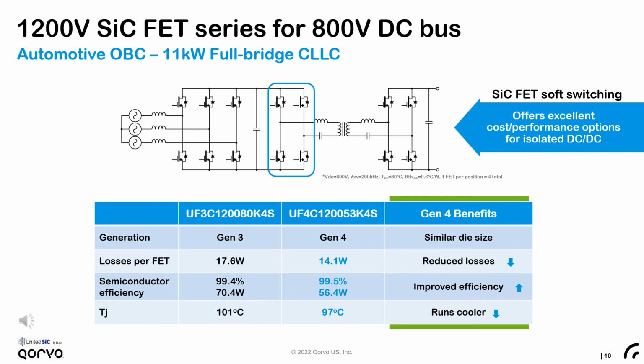Using the new 53 milliohm FET, or the UF4C120053K4S, we see an excellent semiconductor efficiency of 99.5% and a low junction temperature of 97 degrees C. Here, with a similar die size as our previous generation part, our Gen 4 part, with its lower conduction losses, reduces the losses by 20% and runs cooler. Both the new 53 milliohm and 70 milliohm 1200 volt FETs are great cost performance options for the isolated DC-DC converter stage.